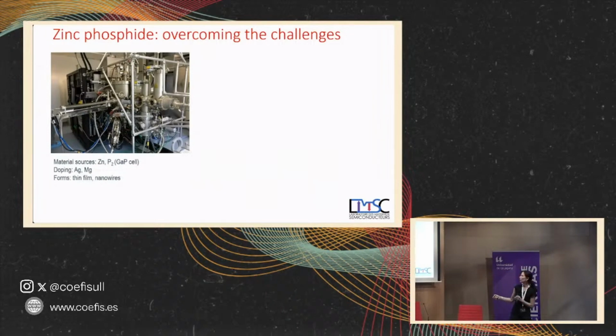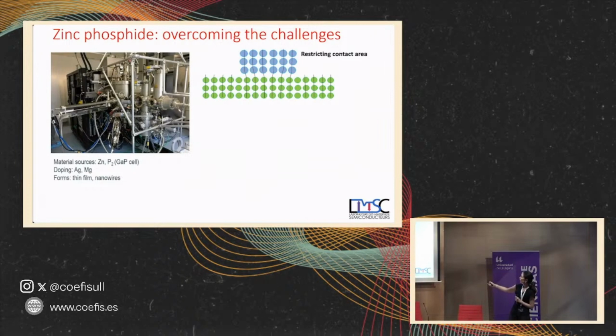Like this, we avoid having a pot of phosphorus here that if something goes wrong, you create a fire right away and you kill the whole building. So we just have gallium phosphide that we let evaporate very controllably in the machine, releasing phosphorus. So a way to avoid this is you can restrict the growth to a very small area.